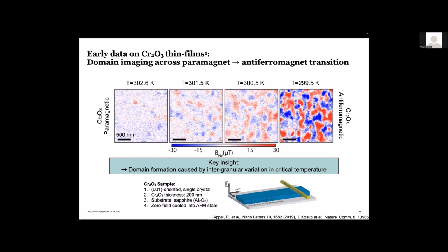So we studied this a few years ago, initially on thin film. So I'll be rather fast here. This is just an example of how we could measure how this material transitions from paramagnetic into antiferromagnetic at this transition temperature of roughly 300 Kelvin, and how this breaks up into domains. Again, here this was on a thin film, and in this work that's cited down here, we're able to essentially investigate why there is domain formation in thin films of chromia.